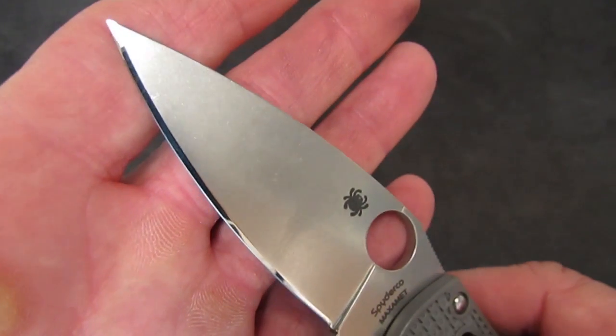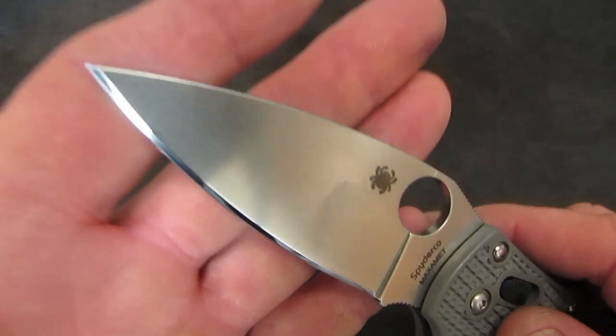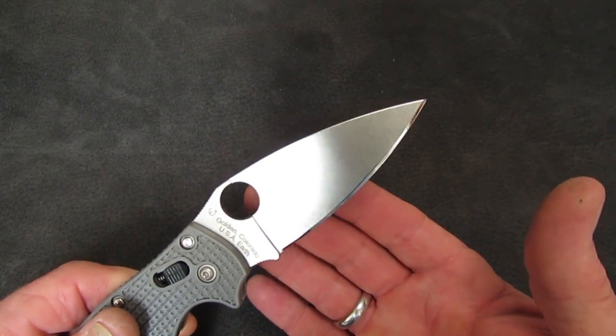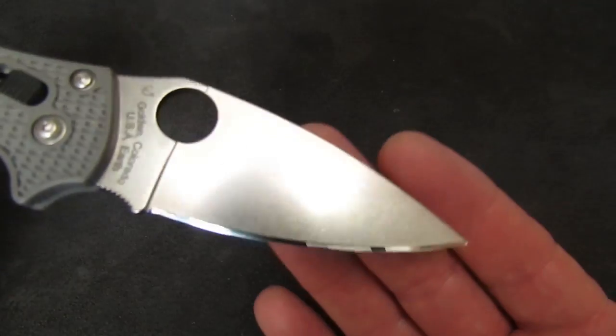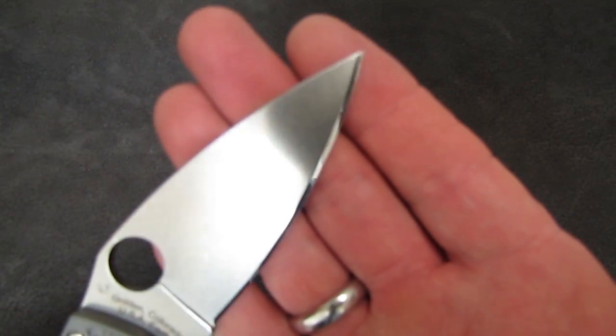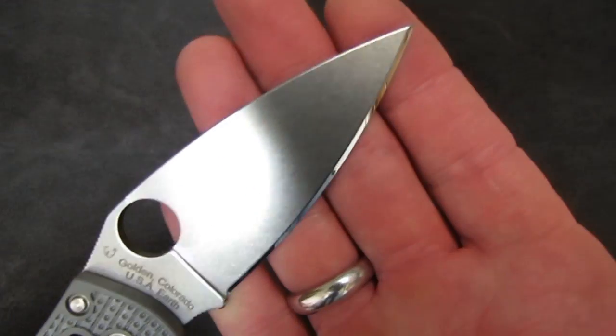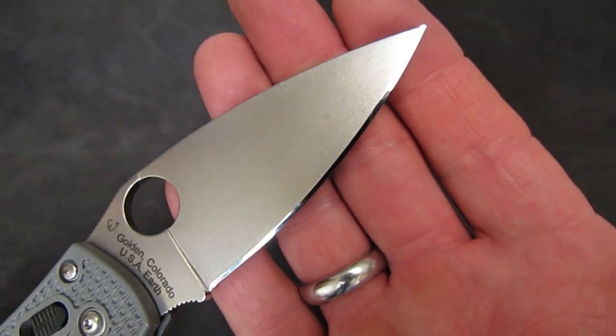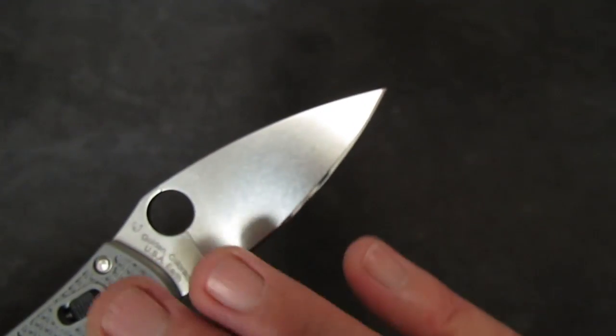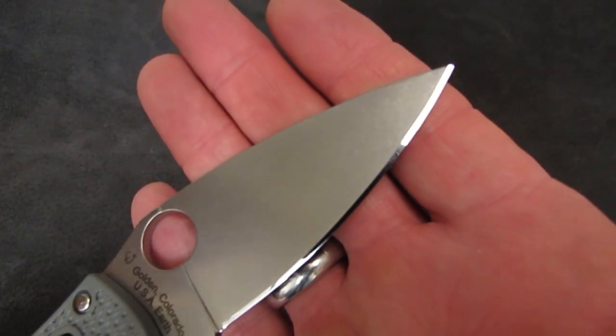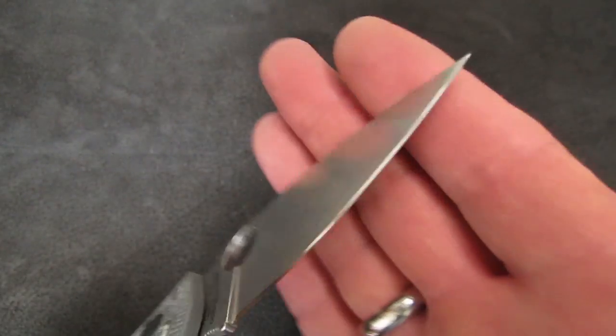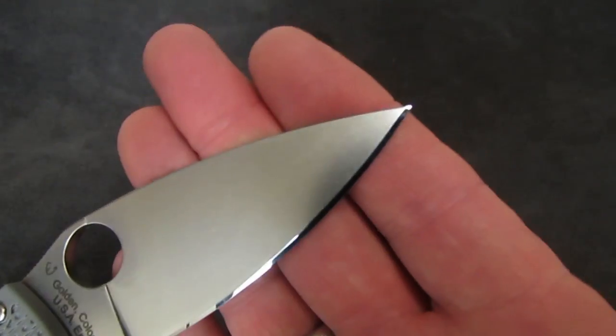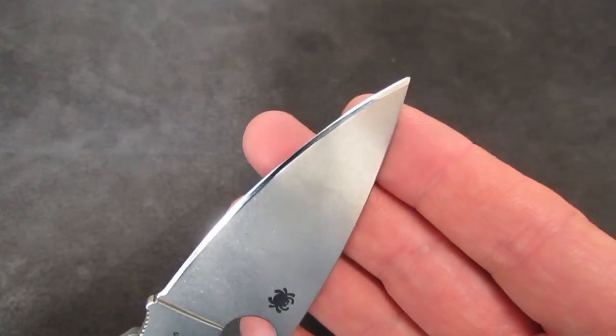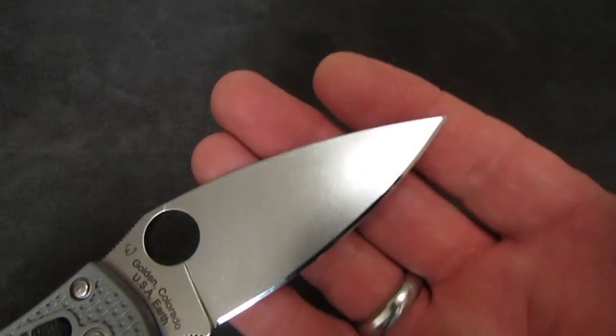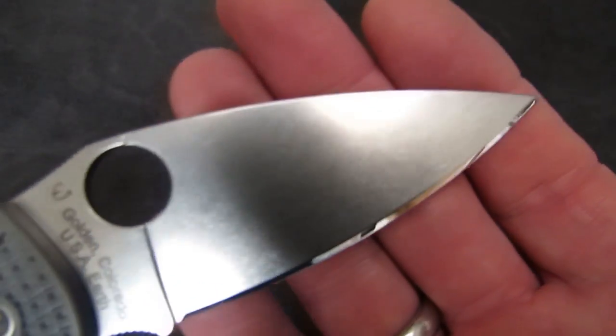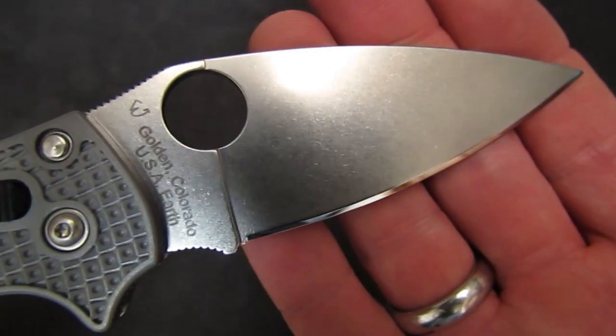Here's what I did. The first thing I did is sharpen the micro bevel at 22 degrees per side. I started with a 600 grit stone, and it was probably polished to 1500 or 2000 from Spyderco. Probably 1500. And it was probably quite convex. So I sharpened at 600 the micro bevel and made it pretty wide. Then went to 1000, still on the micro bevel, 22 degrees per side. Then 2300, and then lowered my angle and just basically refined the scratch pattern on Spyderco's secondary bevel with super light pressure.